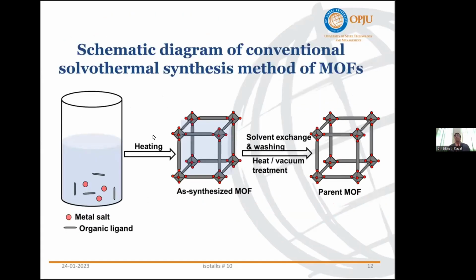Okay, so now coming to how this MOF, the metal organic material, can be synthesized. Basically, the conventional method is the solvothermal method. That means you require some metal salt and some organic ligand. They are taken in some organic or inorganic solvent, and we use an autoclave reactor to create very high pressure, and we heat it. Then after heating at high pressure, the organic ligand and metal salt conjugate with each other and form the metal organic framework material as a three-dimensional structure. Then we do some solvent exchange and washing, and finally we do the drying to collect the parent metal organic framework material.